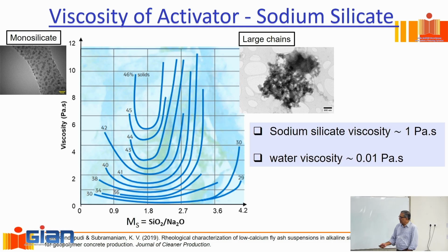If I take the silica to sodium ratio along this side, where my sodium essentially goes down to 0, you'd see the viscosity would actually shoot up again. And when I'm dealing with pure silica, invariably you'll end up with this form here. It's going to be highly polymerized. Now, what sodium helps me do is also control the size of this silica particle in there. But that brings about a lot of complications. My variables, when I'm dealing with this, are much, much more complex.